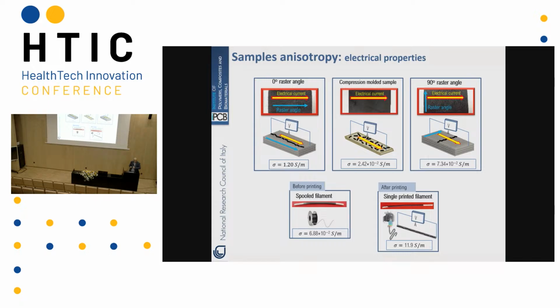Let me show you what the effect of the anisotropy is in this type of material. If you imagine printing a conductive material, like a material that you can obtain from a common thermoplastic material in which you put filler in nanometric shape, then you reach the right composition that is higher than the percolation threshold, you obtain conductive materials. Okay, if you print this and you change nothing, just the direction of printing, you obtain completely different values of the electrical conductivity. So you can go from a conductive material to an insulant. Of course, when I say conductive, don't think of metal conductivity. And when I speak of insulant, it is not ceramic, of course. But for our application, it's enough. You obtain very, very different effects, on the order of 2 orders of magnitude.